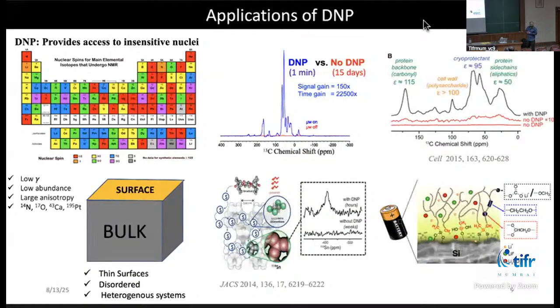So many things which were not possible without DNP are now being done, and DNP is a lot more useful for materials than for biosolids for one reason. And that reason is, if you see this spectrum, there is very low resolution. That is because DNP is done at around 100 Kelvin. So there is a lot of heterogeneity because of conformational trapping. So DNP for biosolids loses resolution, but for materials, it's not a big problem. So at the moment, DNP has a lot more applications for studying materials than biosolids.